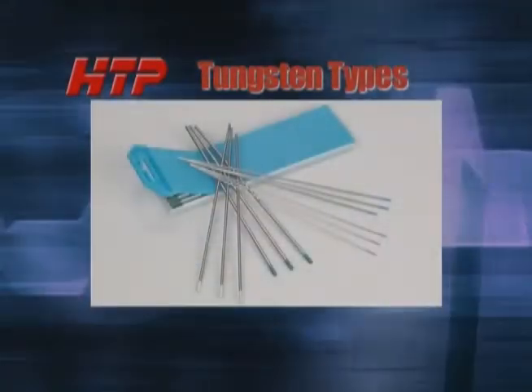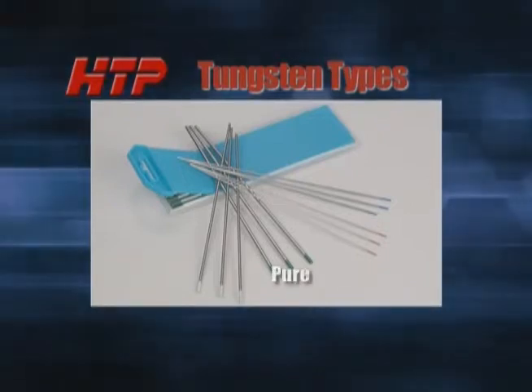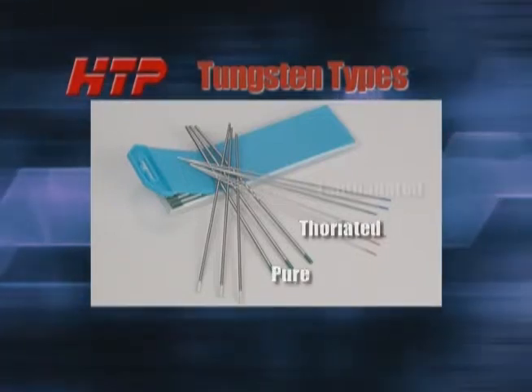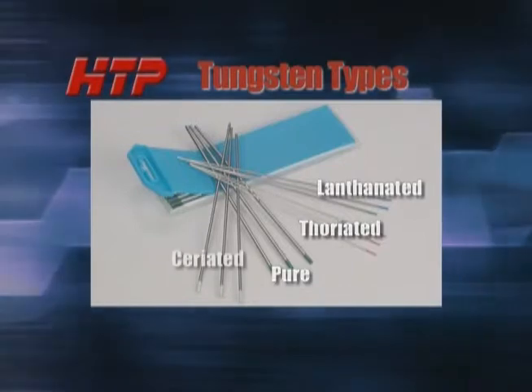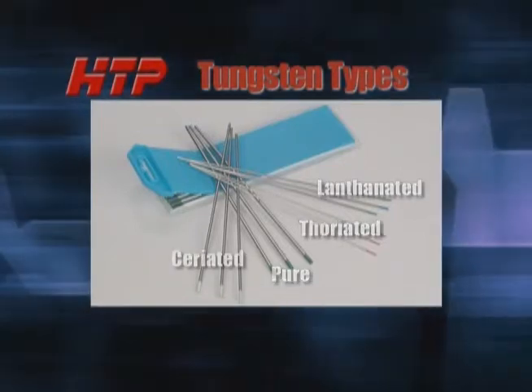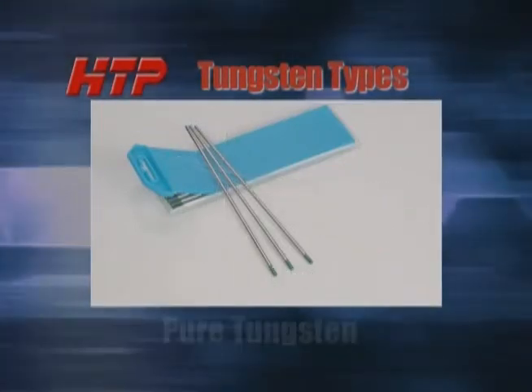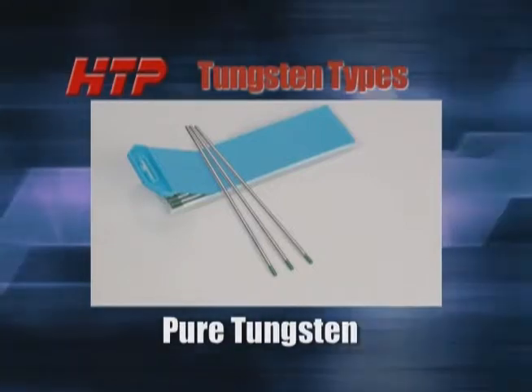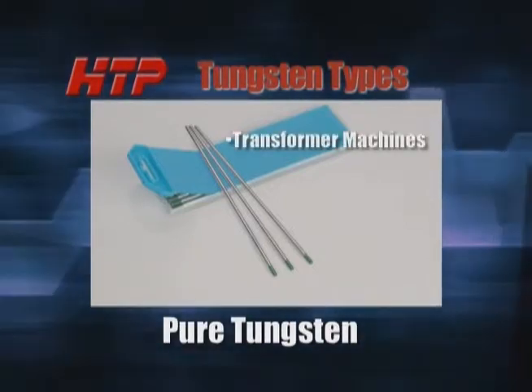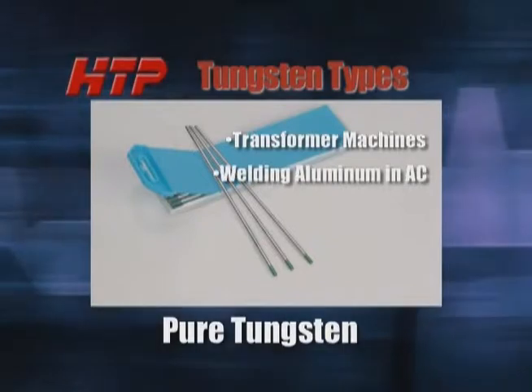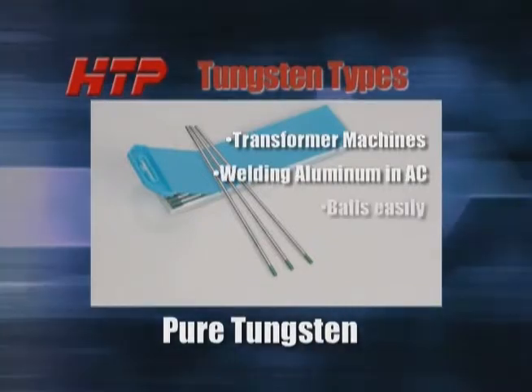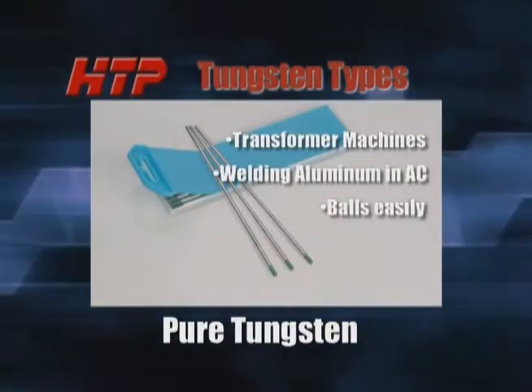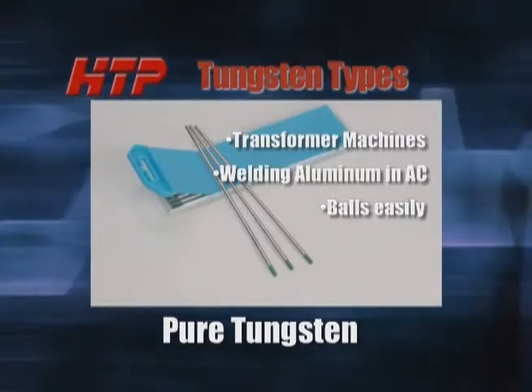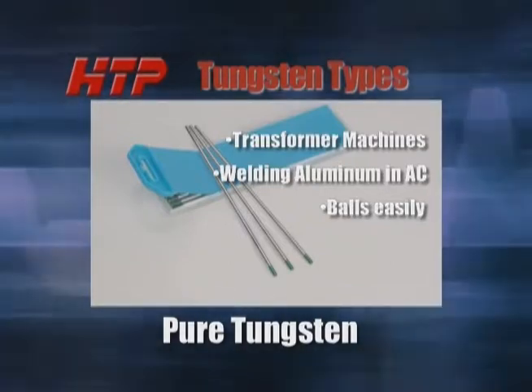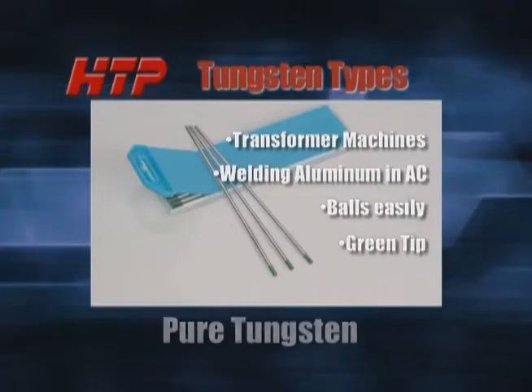There are 4 basic types of tungsten electrodes: pure tungsten, thoriated tungsten, lanthanated tungsten, and ceriated tungsten. Pure tungsten is generally used on transformer-based machines when welding aluminum in the AC mode. Pure tungsten will tend to ball easily. We do not recommend using pure tungsten on inverter-based welders. Pure tungsten is designated by a green tip.